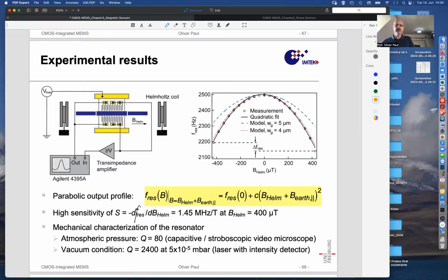And then, what will one observe? Okay, well, at let's say 0 micro Tesla external field, and we're talking about micro Tesla here, we have a resonance frequency of 2,500 hertz. And then when the magnetic field is increased to positive values, the resonance frequency decreases. And when the magnetic field goes the other way to negative values, the resonance frequency also decreases, as expected, insensitive to the direction. Nevertheless, interestingly, you see that it doesn't decrease the same way in both directions.